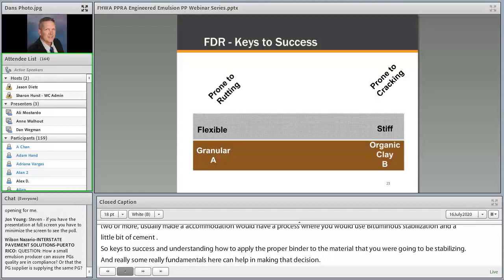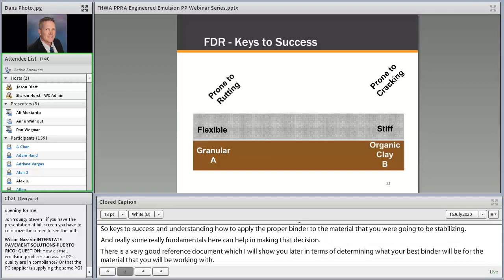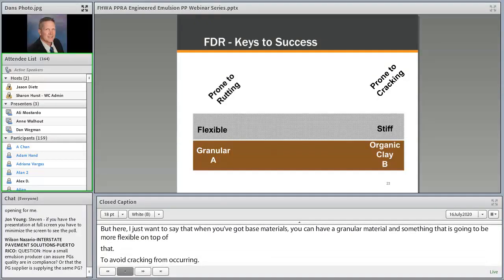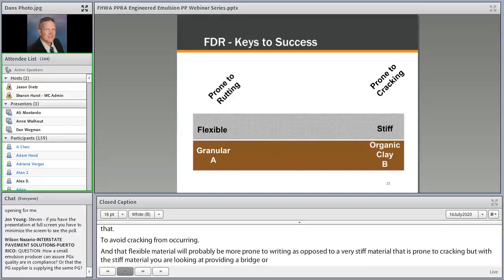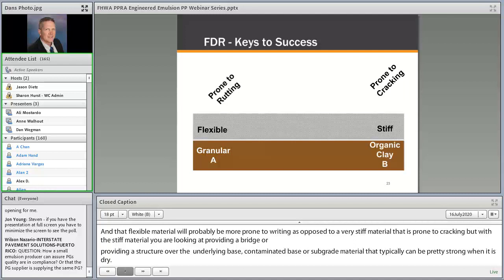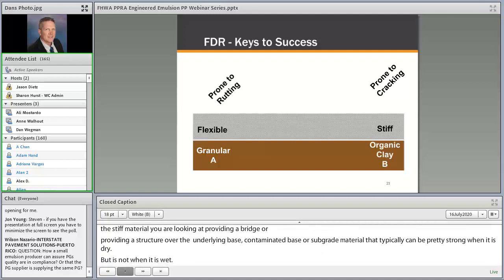But here I just want to say that when you've got base materials, you can have a granular material and put something that's going to be more flexible on top of that to avoid cracking from occurring. And that flexible material will probably be more prone to rutting as opposed to a very stiff material, which can be more prone to cracking. But with a stiff material, you're really looking at providing a bridge or providing a structure over underlying base, contaminated base, or subgrade material that typically can be pretty strong when it's dry, but is very weak when it gets wet. So you want to be able to put a bridge over that so it's got enough strength to be able to withstand the weakness of the underlying material if it should get wet.